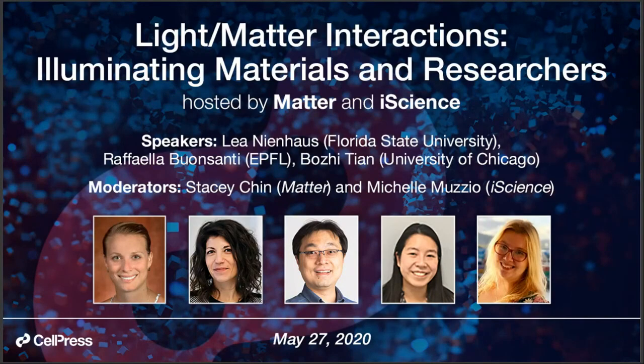So the first question is, in terms of these nanoplatelets for upconversion, is the geometry or the confinement important? And would you expect similar results on simple nanometer thin films? That way you don't have to worry about the stacking. So nanoplatelets are just confined in one direction. Nanometer thin films, I would, to first approximation, expect a similar behavior. However, I believe that you probably would introduce so many trap states that the whole process wouldn't occur.